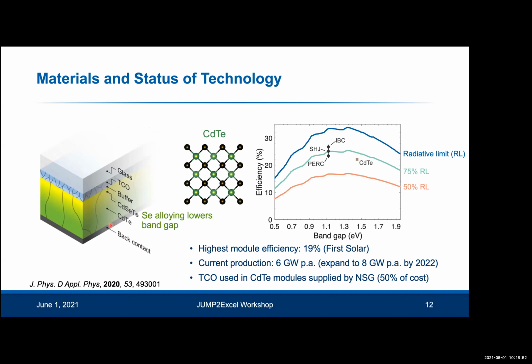And what is being done to get the best efficiencies now is to alloy selenium into cadmium telluride, which lowers the band gap and improves its spectral match with the solar spectrum. So, the best efficiency reported for cadmium telluride is about 22%, which is very close to the 75% of the radiative limit line. And the highest module efficiency is very close to that. It's reported to be 19%, and that's reported by First Solar.